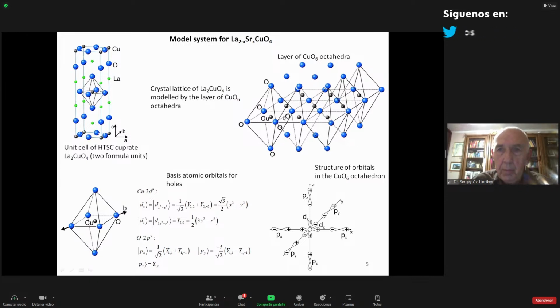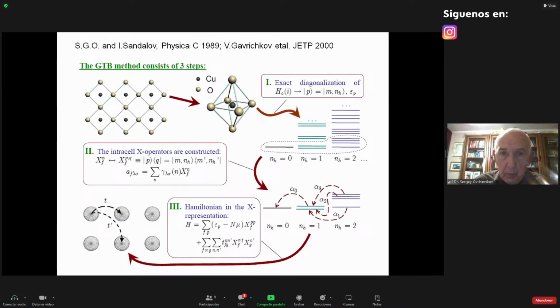This is the La2CuO4 structure, and one CuO6 cluster is a unit. We consider it as a unit cell of our lattice. On the first step, we take all the important atomic orbitals: the dx2-y2 and dz2 orbitals for copper, and three orbitals for oxygen, x, y, and z oriented p orbitals. All these orbitals are shown in the right picture below, with the overlapping of these orbitals. Then we perform exact diagonalization of this cluster, including Coulomb interaction on copper, on oxygen, and between copper and oxygen.